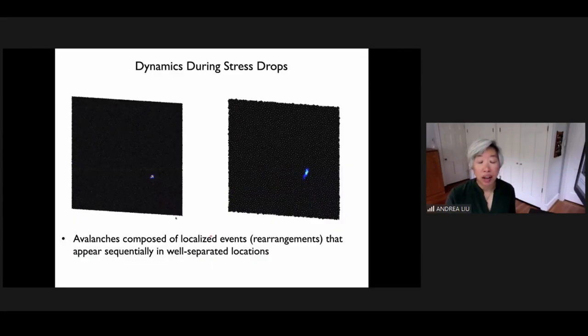But if you look at what's happening during the process, it looks very similar. So here's the ductile system. What you see during a stress drop is localized rearrangements that fluctuate around and then hop from one location to a rather distant location. And if you look at the brittle system, it looks the same. You see these things that hop around. It's just that all the rearrangements in the case of the shear banding system are concentrated in this region where the shear band is.